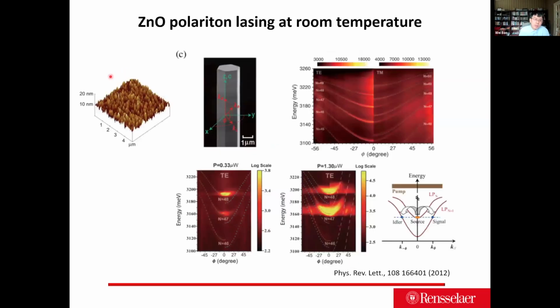Same thing with zinc oxide. If you grow it with various methods into a two-dimensional film and then measure on top of the surface, it tends to show quite a bit of inhomogeneity. So people got rid of this two-dimensional difficulty by running synthesis with one-dimensional nanowires and demonstrated polariton lasing in this Physical Review Letters paper. But this one-dimensional nanowire configuration also has a lot of limitations in studying polariton physics. For example, if you try to construct a potential landscape, a one-dimensional system tends to be very hard.